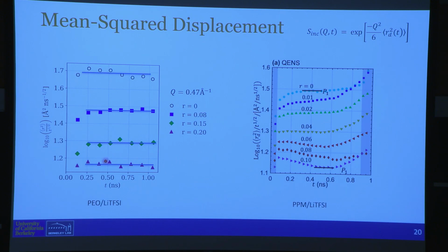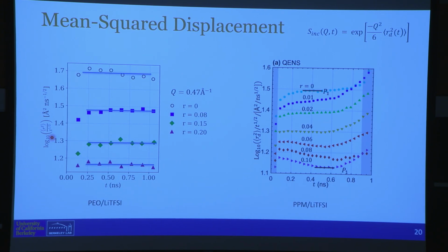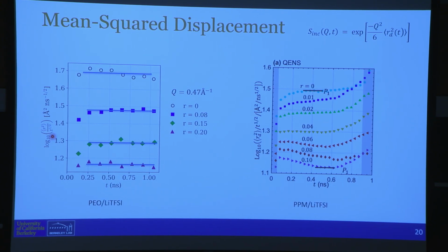And here's the data plotted. Mean square displacement normalized by t to the half power, 0 salt, and as salt increases, you get a plateau, and the plateau comes down. And that is because of the increase in friction as you are adding salt. Okay? This is 1.5 angstrom square per nanosecond to the half power. And this we published some time ago.